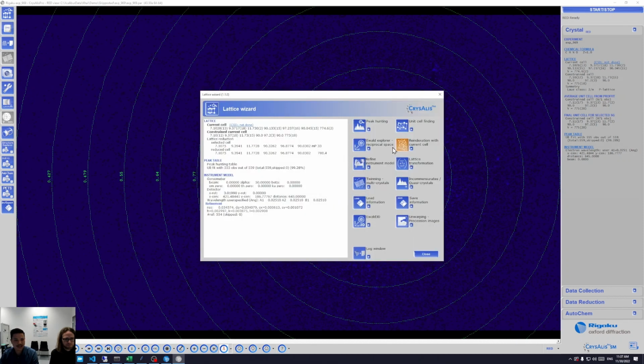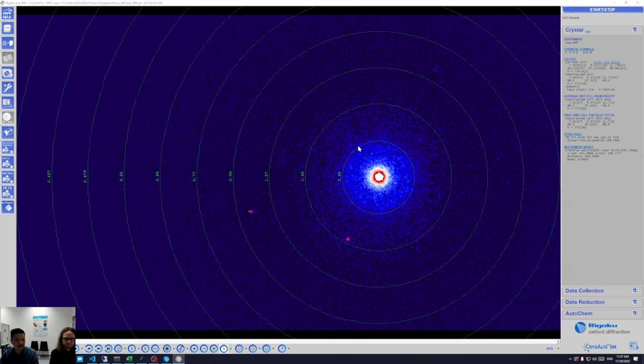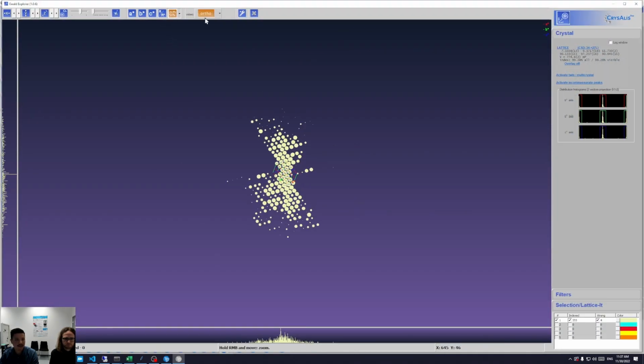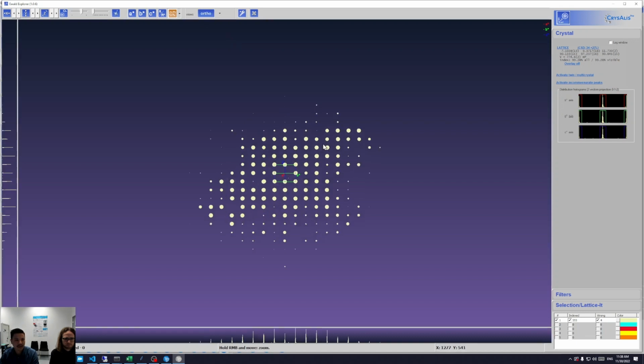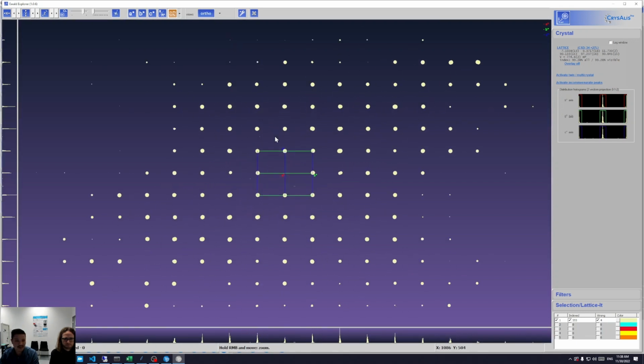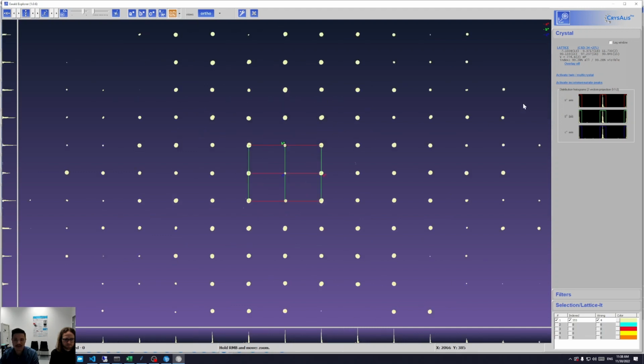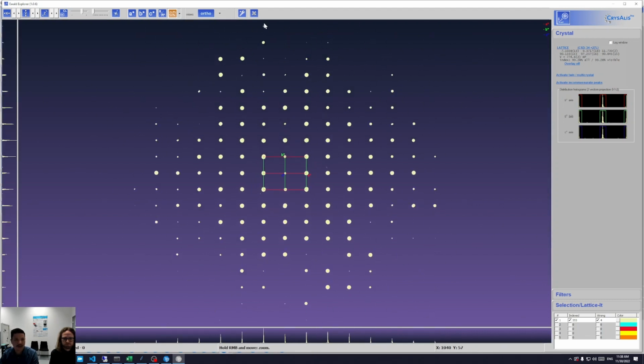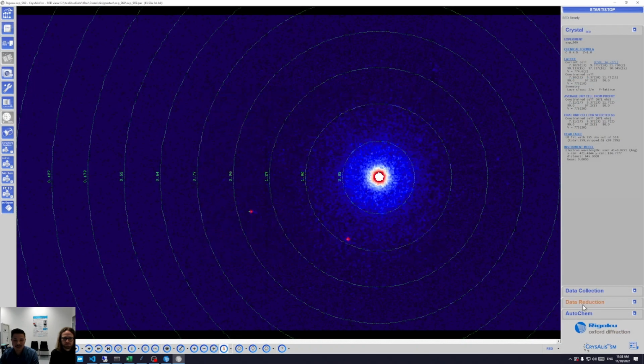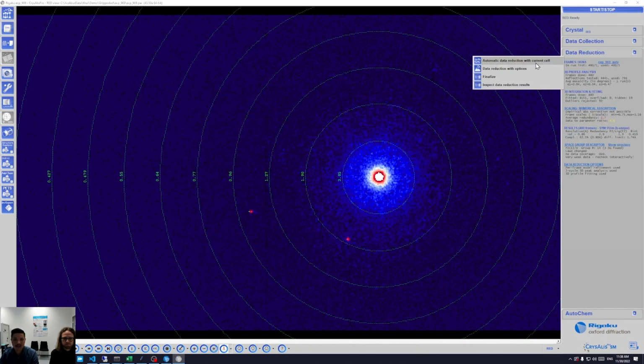And in this case, we have already indexed almost 100%, 99.3% of all index spots. And if we have a look in the eval explorer, we could see that it matches up quite well to this monoclinic primitive unit cell of paracetamol. So the next step would be to do the data reduction.